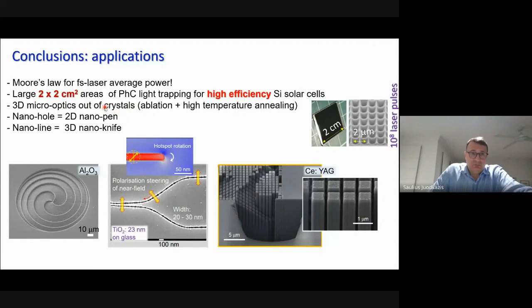And the final 2 examples, 2D, just a nano-hole, which was used as writing for 2D patterns on the plane surface. By the way, this is collaboration with Jilin University, and the group was also showing that you can write 2D patterns on curved surfaces, not flat surfaces. With electron beam lithography, you can't do that, but with femtosecond laser, looks like it's possible. And the final thing, which is still in review, but it will be published probably this year, we hope, is that you can use nanoscale writing, which was improving resolution by 2 orders of magnitude and aspect ratio by another 2 orders of magnitude for current 3D machining by absolutely whatever is the technique. So here, femtosecond laser writing is really standing out as a good tool.